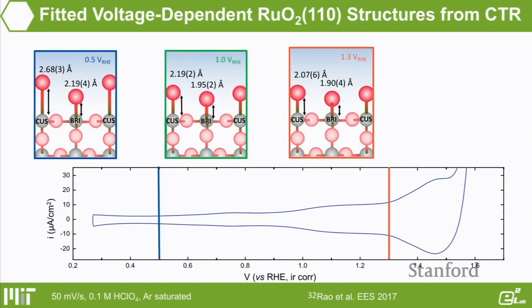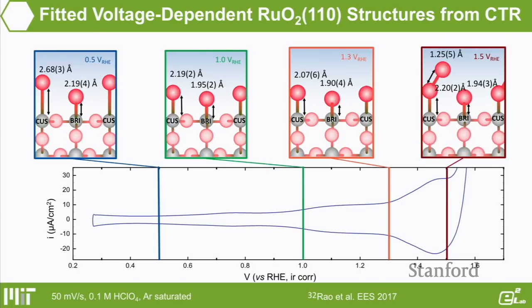Utilizing this information, what we can do is deduce the oxygen distances bound to the CUS ruthenium and to the bridge ruthenium. Initially at a low potential, you have a surface where typically you might have some water adsorbed on the surface of ruthenium dioxide. As you can see from the measurement, on the CUS site you have some oxygen bound quite a long distance away, and then on the bridge, a little shorter. And as you increase the potential, as we know, it gradually will oxidize water to become OH and O and O2. So essentially you see the oxygen distance is actually getting shorter. And then at 1.5 volts, essentially the turnover potential for oxygen evolution, we see an O2-like species adsorbed onto the CUS site.